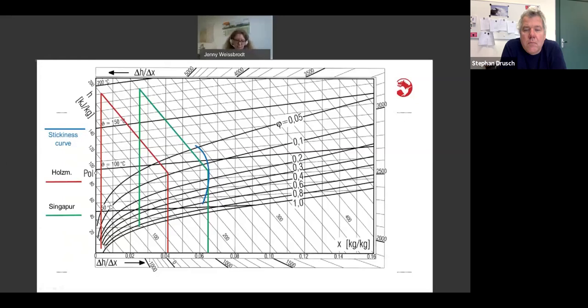So let's have our drying experiment with the conditions I mentioned before. So 5 degrees C, moderate relative humidity in Holzminden. What does drying mean? Drying means that we at first have to heat up our drying air. So in this example, I used 190 degrees C for our drying air. And what happens now during drying is that your drying air will give its energy to your liquid droplet to evaporate the water from the surface, and at the same time will take up water from this surface and transport it away. This means that your drying air will cool down and get more moist over the drying process. And this is what this line here represents.